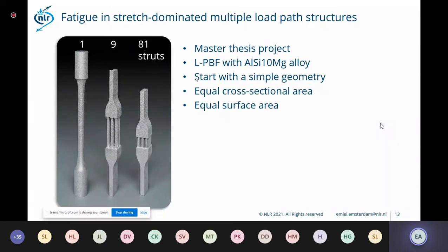As I mentioned before, fatigue is a stochastic process, and usually fatigue cracks start at the surface, especially for additive manufacturing. If you have more surface, there are more possibilities for cracks to initiate. So fatigue life is also a function of the surface area of a specimen. In these 3 specimen types, we kept those 2 the same, the cross-sectional area and the surface area, and that's why the specimens with 81 struts are less long than the single strut specimen.